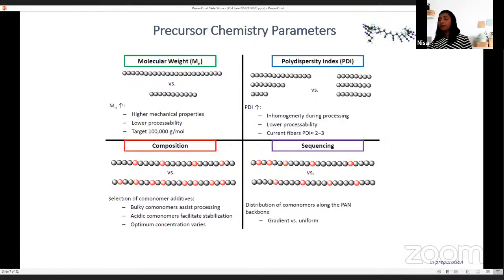So there is a strong demand on carbon fiber manufacturing industries to meet the demands arising from various sectors. But the challenge is, though carbon fibers have been known for more than 40 years, most of the details about carbon fiber production are still unknown, because the exact composition of each PAN fiber varies from one company to another and is generally considered a trade secret. So we only have some indications, like the quality of the carbon fiber is directly dependent on the precursor.